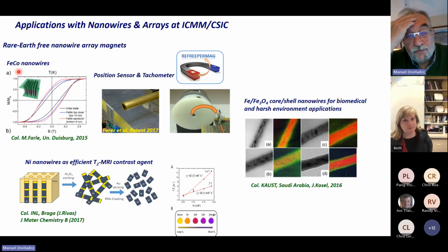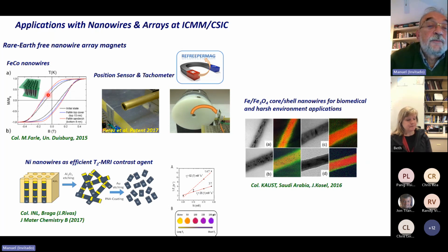The problem is that the nanowires are relatively close to have a larger density of magnetic moments, but they are interacting magnetostatically. That reduces a bit the remanence and coercivity. But we were able, in collaboration with Professor Farle in Duisburg, to put some ferrimagnets in the ends of the nanowires to delay the reversal, the nucleation of the domain wall.